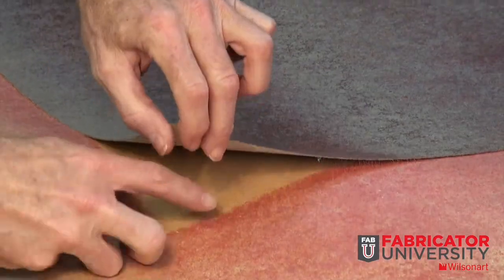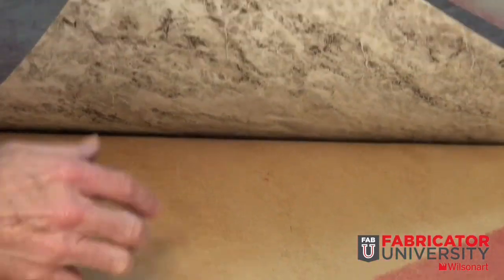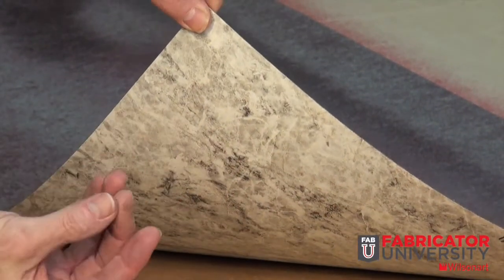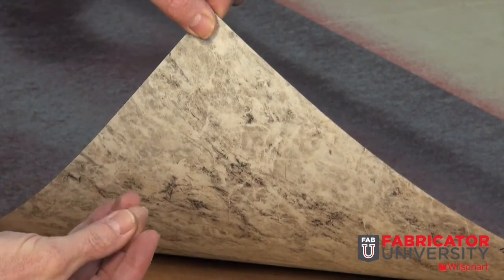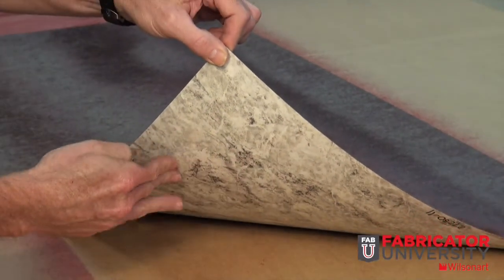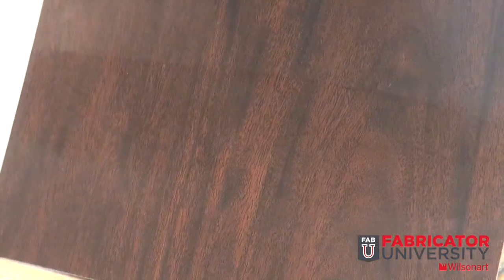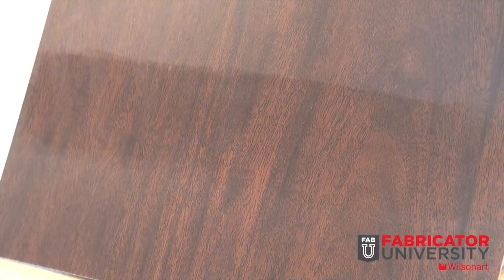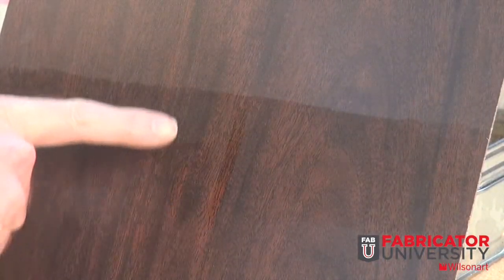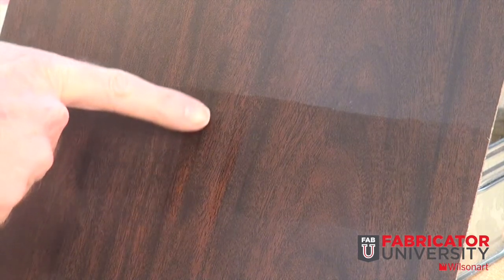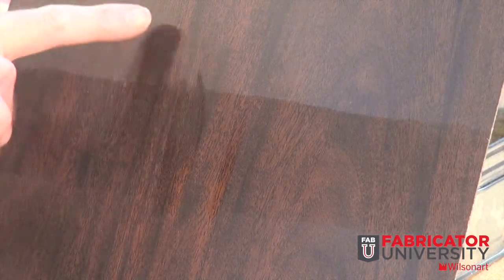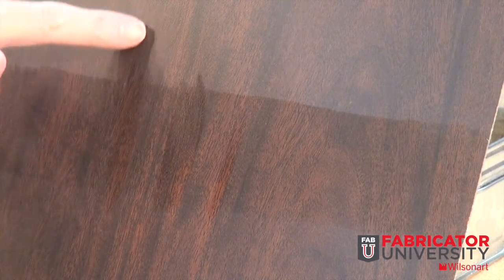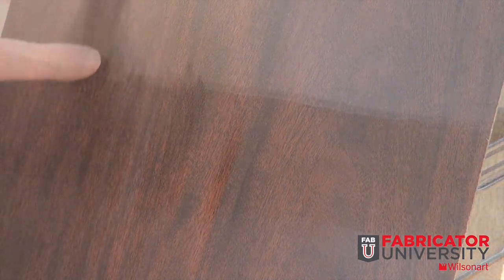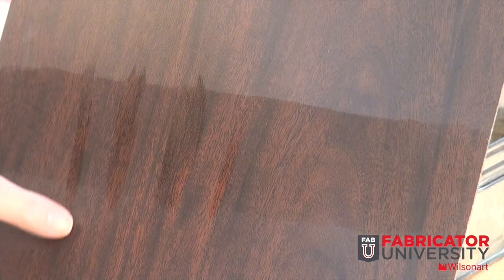Excessive blushing of the laminate face is a good indicator that excessive amounts of adhesive have been applied and/or the humidity is too high and may require extended dry time. If there is moisture on the laminate face, it's very likely on the adhesive layer also. The blush is caused from the rapid evaporation of the solvents, which causes the temperature in the immediate area to drop. When the temperature reaches the dew point, moisture will form on the surface of the adhesive. This moisture will interfere with the two adhesive layers making contact.